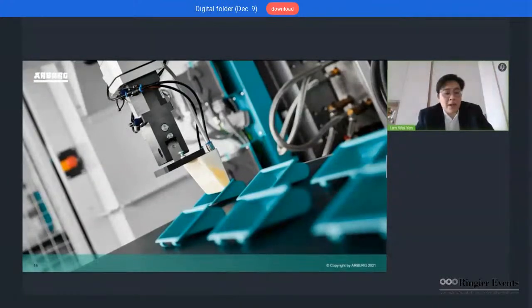So designing this part also gives us the possibility to present these two material printing. The second advantage that we get from such an approach is that we can automate the process without the need to remove the sprue. The sprue is normally the plastic residue from injection molding. The traditional gripper was not suitable in this case because of the limited space between the mold openings and the position and orientation of the part in the mold. This is the reason why we had to develop an alternative.